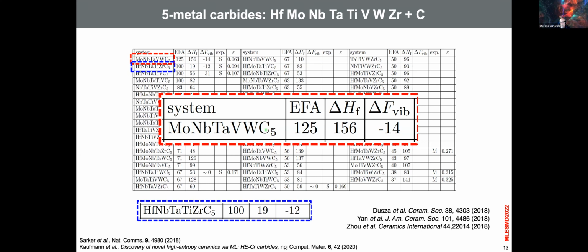So in fact, it was not predicted by experiments, and the only way to find it was our systems. Look here, the loss in enthalpy is very high, meaning that this is very high from the bottom of the convex hull, but it still has the highest possible entropy forming ability. Still, this material was found. So you see that nobody here, we are all computation here, would ever even bother calculating an excited state with 156 milli-electron volts per atom.